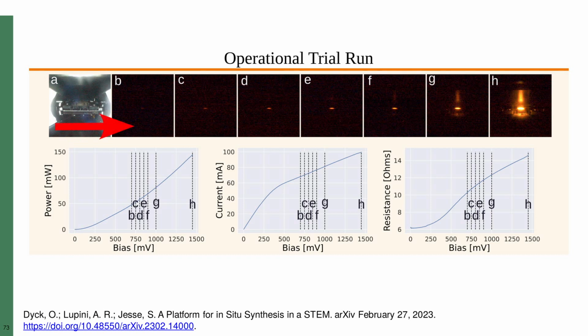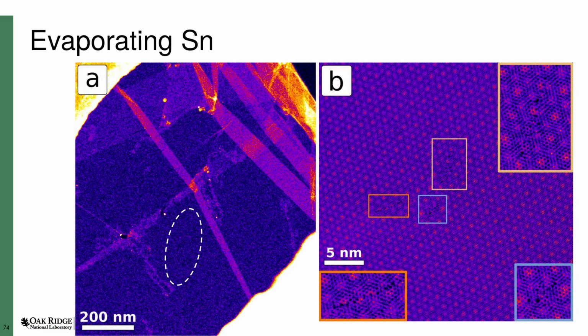Then we switch the light off and activate the heater filament. So far so good, the heater works. Now the real test. We put a thin coating of tin on the heater filament and put it back in the microscope with another twisted bilayer graphene sample. The graphene is sitting on its own heater chip, so we can heat it independently from the filament.